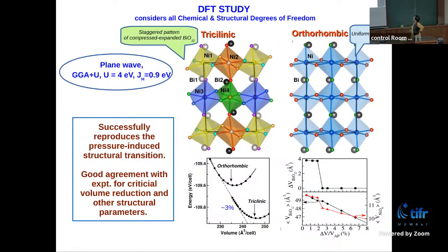So we did some density functional theory calculations. I will not go into the details of it, but this just shows that density functional theory is capable of capturing this volume collapse and also the change from the ambient pressure to the high pressure phase, correctly showing the transition. And we even had very good agreement with all the structural parameters of the ambient pressure phase and the high pressure phase, saying that density functional theory is able to capture the essential physics.